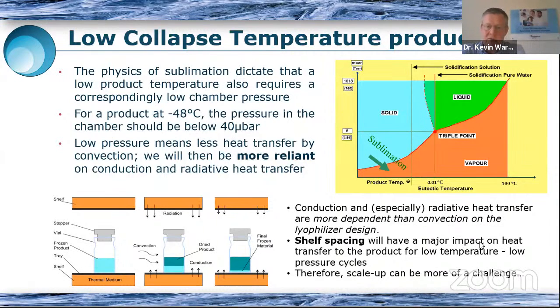Fewer people having issues with reconstitution, but again, that can sometimes be affected by the cake itself, and of course that's highly dependent on the active ingredient as well. So very interesting that cake quality is a pressing issue, and actually, as I mentioned, one of the instruments we've developed much more recently is the MicroPress, which is a structural mechanical testing device for freeze-dried materials, and it's designed to look at them in situ in the vial or in whatever container they're produced in. So we don't have to take a sample physically and use an offline method to look at the structure and the Young's modulus and the strength. We can do it in situ. So we are trying to do our bit in making certain aspects like this more quantifiable for quality purposes.